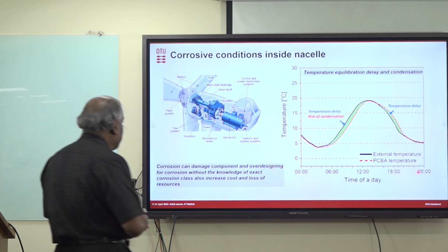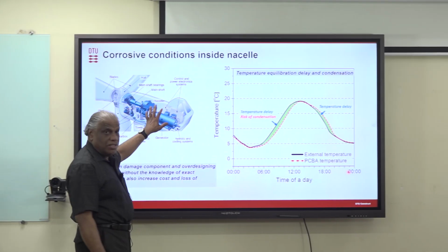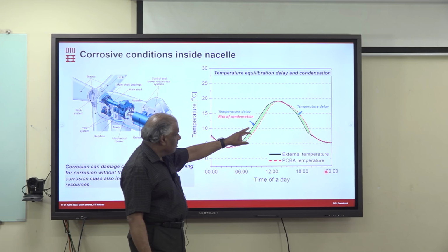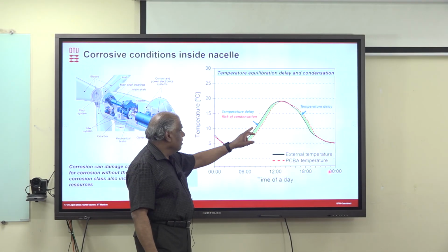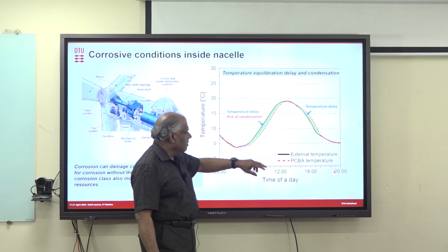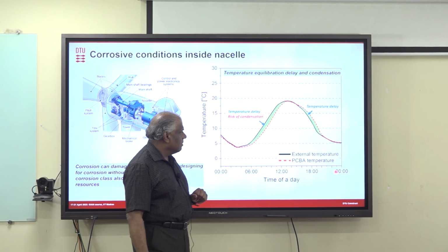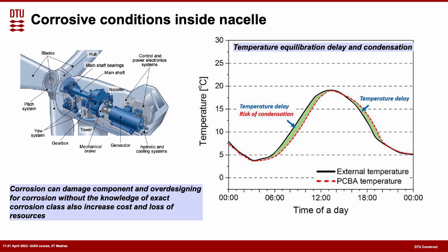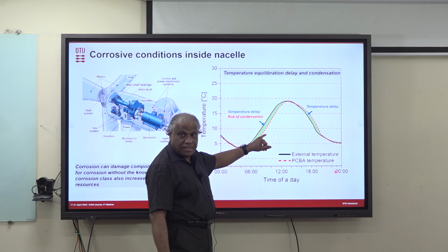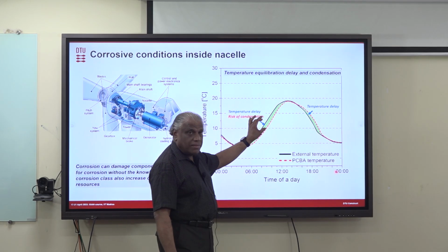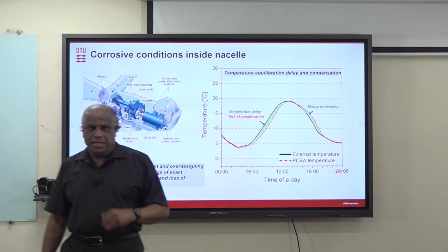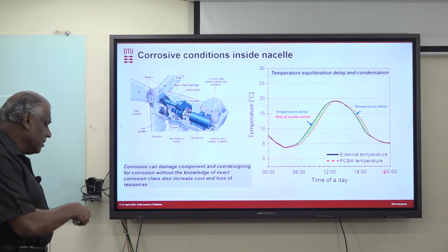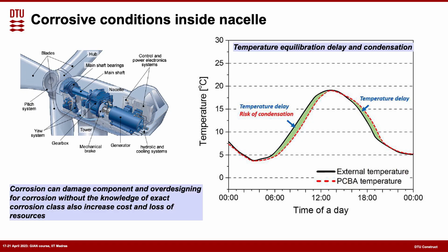This is exactly what happens in the nacelle. Overnight, if the nacelle is off, because of this delay, that is what is shown here. This is with a PCBA, but there is a delay between the PCBA temperature and the external temperature. What you can see is that the external temperature is rising, but the PCBA temperature is still colder. This difference is what makes the condensation inside. The PCB is an example, but you can think about any material sitting inside, and that causes condensation at many different parts because they are heavy metallic parts, and then you get the corrosion problem.